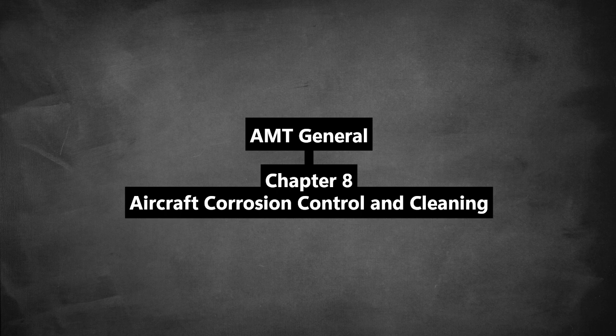There are also chemical treatments that convert rust to a passive phosphate layer, but generally not for assembled aircraft due to rinsing issues. And chemical inhibitors are usually a bad idea on installed parts due to entrapment risks. What about highly stressed steel parts? Any rust seems critical there. Absolutely critical. Removal must be very careful, using only mild abrasives: rouge, fine aluminum oxide, fine buffing compounds, non-woven pads. Don't overheat the part during buffing. Reprotect immediately with paint. Chemical removers are generally forbidden without specific engineering approval due to the risk of hydrogen embrittlement, making the steel brittle. Right.